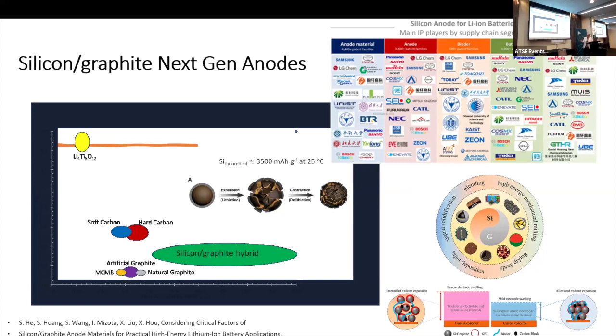Now, the issue with graphite is that it doesn't have a very high capacity for lithium. It's down in this region. Oh, sorry, the axes haven't come through. It's about 372 milliamp hours per gram. A lot of the markets are looking at introducing silicon into the anode. Around 10% silicon goes into the anode because silicon has a very high specific capacity. If we introduce that, we can get up to about 1,000 milliamp hours per gram from our anode, which means we can have lighter weight batteries. We don't need as much material in our batteries for the matching cathode.